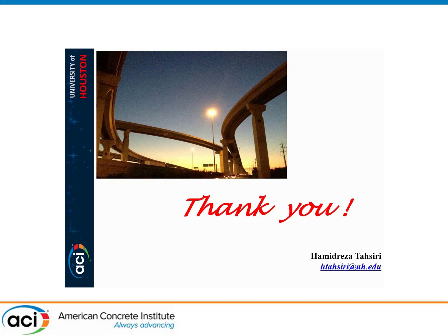It's a very, very good presentation, but only a small comment. I think the result that you got applies specifically for the material that you tested, because I saw an example for the CFRP bars of some interlaminar shear failure. Yes. And this is really a fiber matrix interface problem. Yes. And maybe the bars that we tested are made with carbon fibers and vinyl ester, which is not really compatible, because most carbon fibers are compatible with epoxy resin. So we'll test some CFRP bars made with carbon fibers and epoxy. I'm sure that you will get different results. Sure. Thank you so much for the comment.